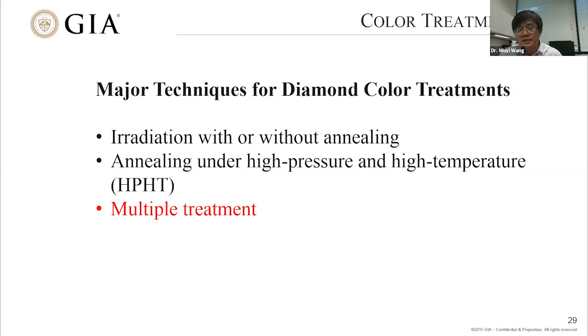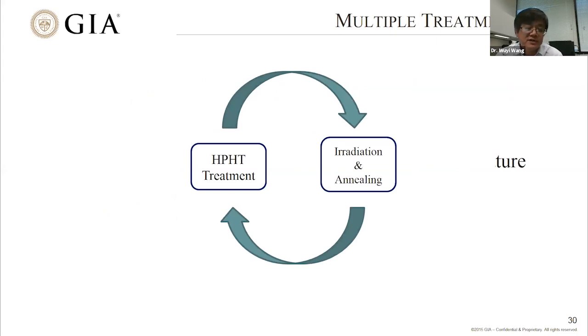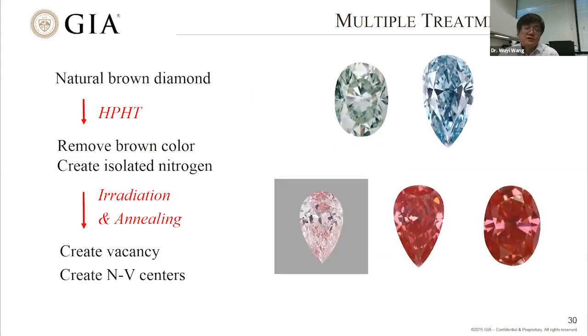So of course, it's very easy to say, why don't we combine these two technologies to create more opportunities, more options. So that's the multiple treatment. The multiple treatments take advantage of irradiation, annealing as well as HPHT treatment to design the best method to reach the best color. What I try to show here is if we have a brown diamond, for example, either type 1A or type 2A, if type 2A after HPHT treatment, the brown color will be removed. If 1A, the brown color will be removed, and it may introduce a little bit of isolated nitrogen. And this stone could be colorless and near colorless, or very slightly yellow, but immediately after HPHT treatment, if these stones are irradiated, they could turn to a beautiful blue like this color, or turn to some green color.